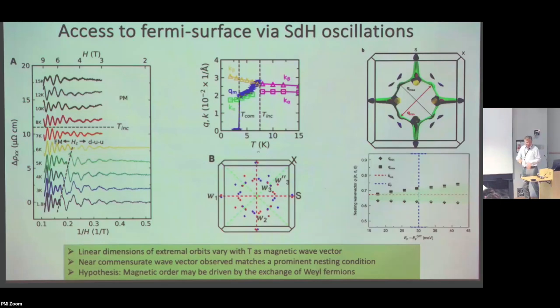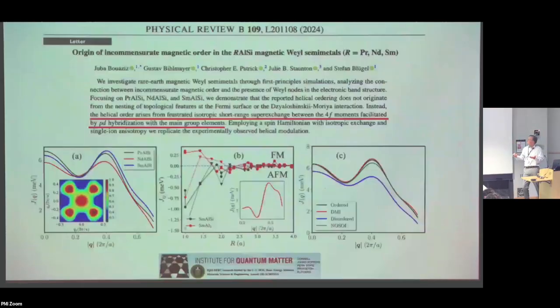So we published a paper that has many of these things and others that I'll have later in the talk, and there was a kind of a response paper that came to that, from this group. They said, listen, we've calculated, using LDA plus U, the exchange interactions in the system, simply by finding ground state energies for different spin structures. And what we find is that the exchange interactions do tend to stabilize this particular structure that you observe with that particular periodicity, but we can make it stabilize that structure even in the absence of Weyl points. So they specifically introduced, by modifying the crystal structure, what are called mirror planes, which eliminated the Weyl points, and yet they still had the same kind of wave vector coming out from it.